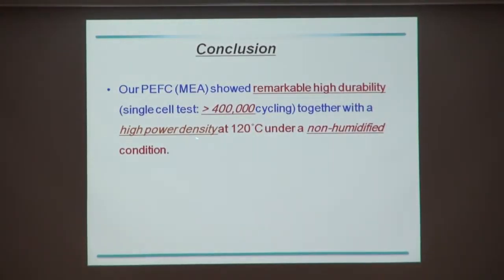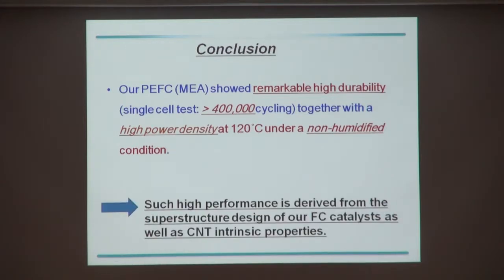Yeah. So the conclusion of this part is that our fuel cell catalyst or MEA showed remarkably high durability in the durability test. That means for 400,000 cycles, our fuel cell is tough, alive, and the experiment was carried out non-humid and at higher temperature, and performance is also very high. So that's our conclusion. Such high performance is derived from the superstructure design of the fuel cell catalyst, as well as the carbon nanotube intrinsic properties. These intrinsic properties are very important.